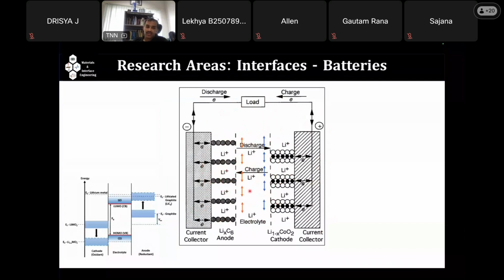It will degrade the electrolyte, and thereby your electrolyte will be completely used up by the electron transfer process. But this solid electrolyte interface will allow lithium transport across the junction, but at the same time it will not allow the electron to transfer. So there won't be any electron transfer across this particular solid electrolyte interface. And this is very important to establish a solid electrolyte interface. Now most of the battery problems are due to the absence of a solid electrolyte interface.